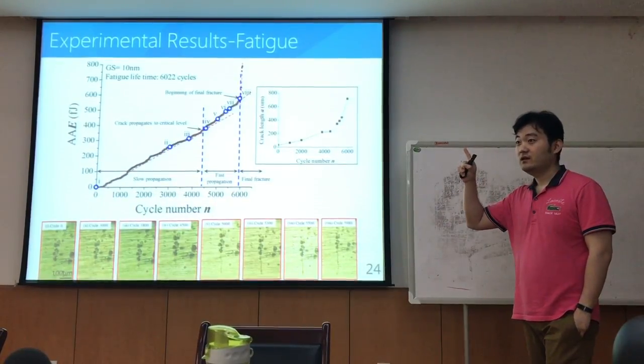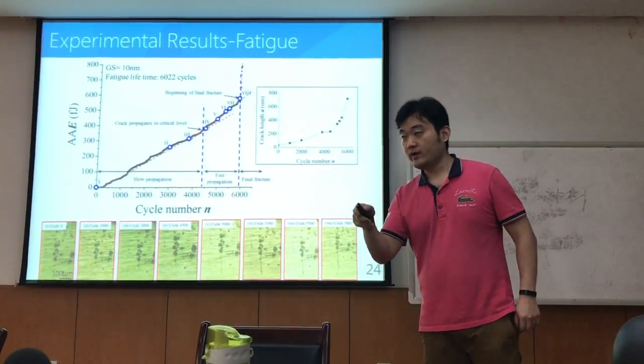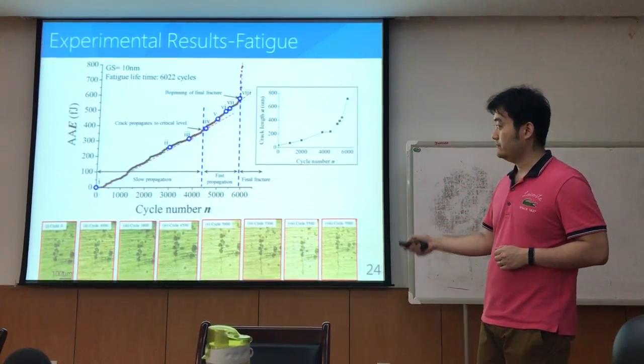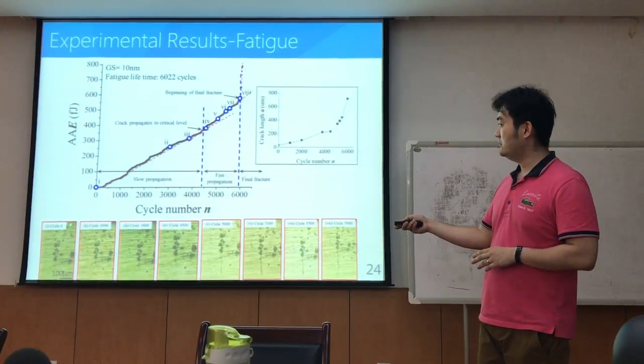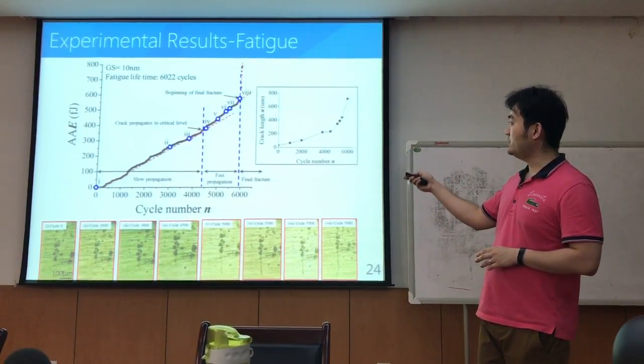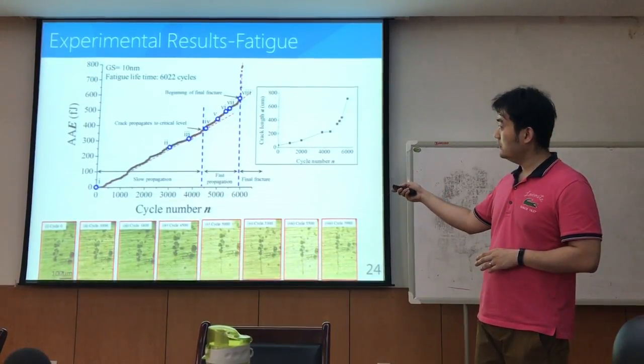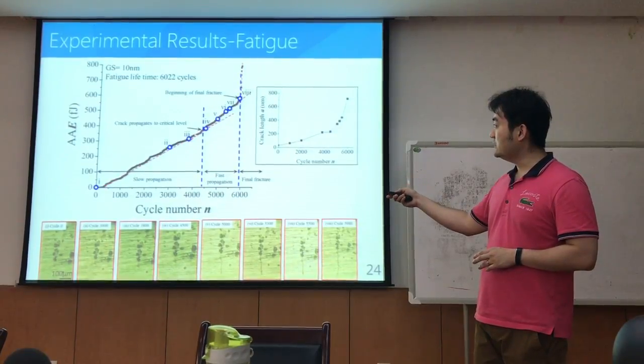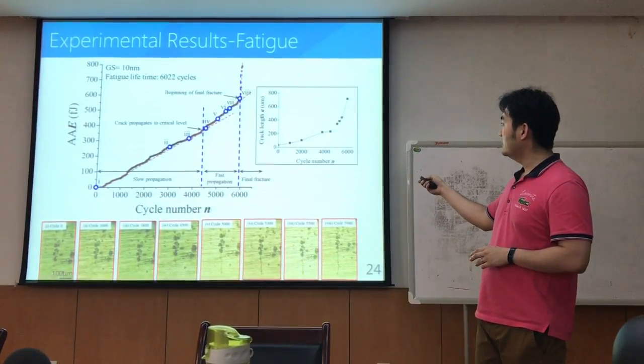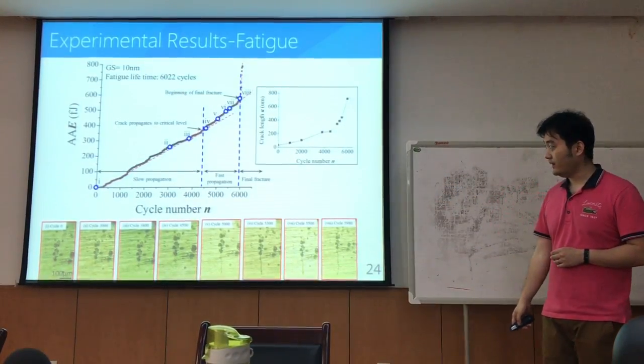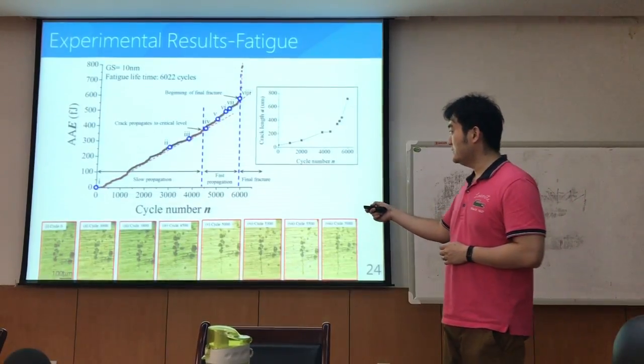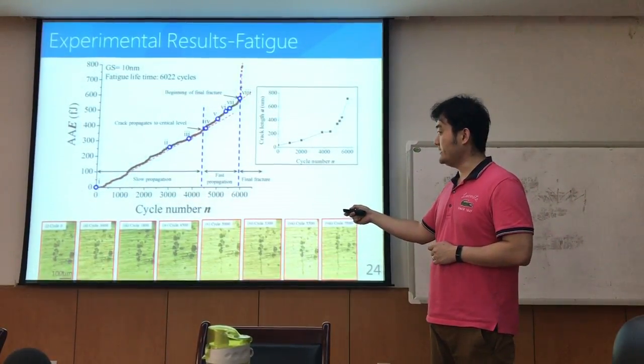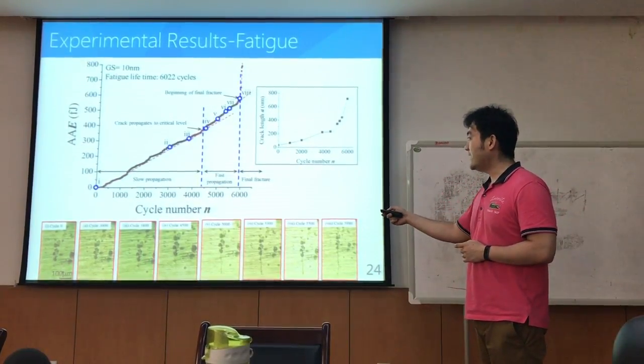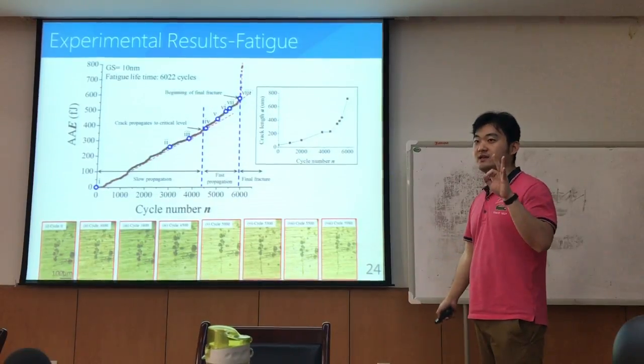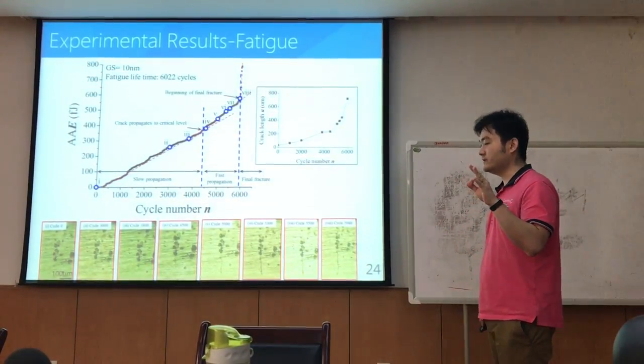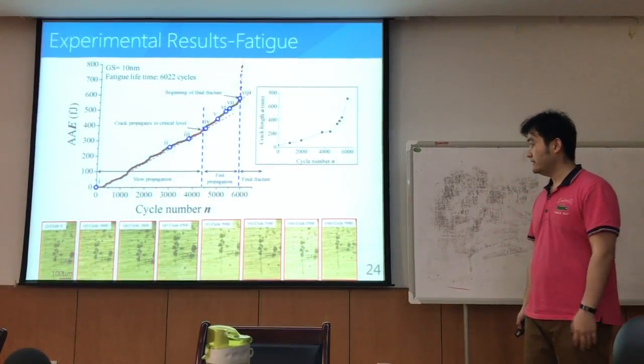Okay. Remember, we use an acoustic emission sensor, and by recording the accumulated acoustic energy, we can separate the fatigue process easily by using different slopes. Okay? And this different slope means different crack propagation speed. So we can separate the fatigue process into about 3 sub-processes. One is slow propagation, the other is fast propagation, and final fracture, which are 3 typical steps for fatigue fracture. Okay?